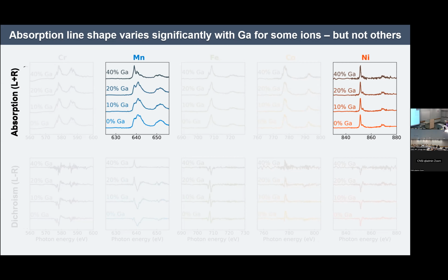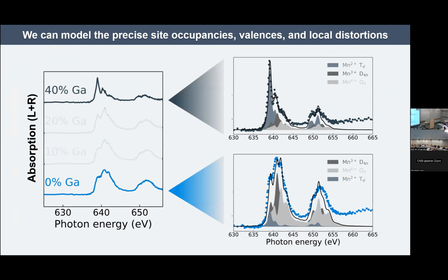When we look at manganese, we see that there are 3 main peaks in this L3 edge. And as we add gallium in, the relative spectral weight of those 3 signals changes dramatically. To exactly quantify how this changing spectra relates to the changing composition of the material, or to say it differently, to understand how our 5 transition metals are occupying those 2 sublattices, we can perform multiplet calculations where we're approximating the strength of the crystal field that's coming from our oxygen ligands and model these absorption spectra.